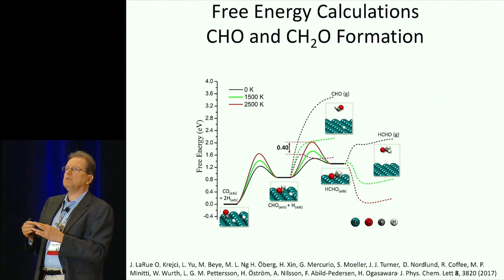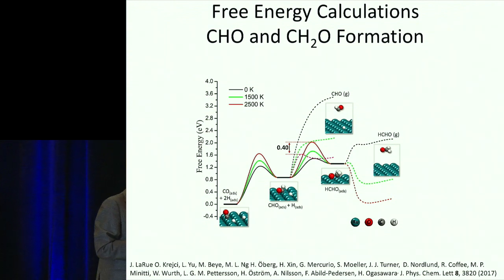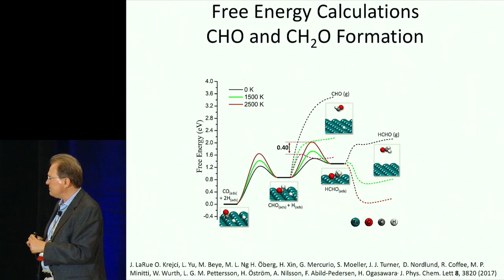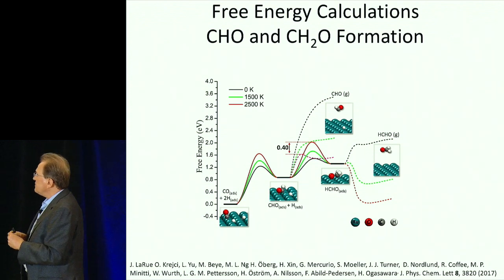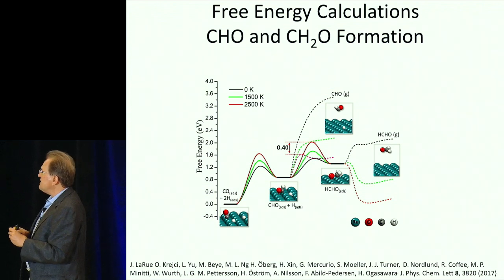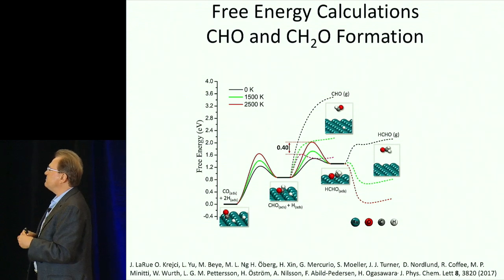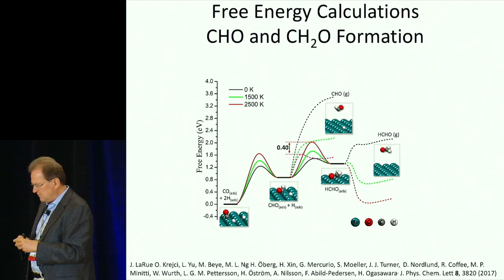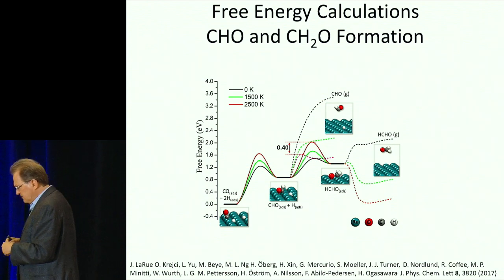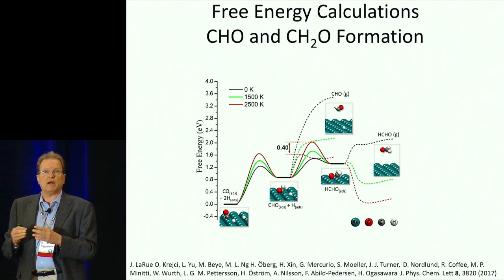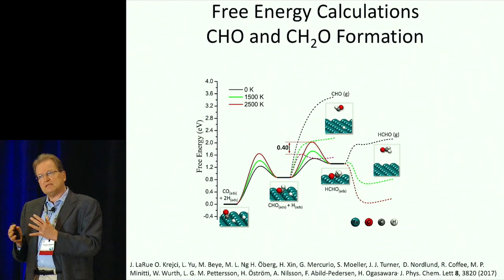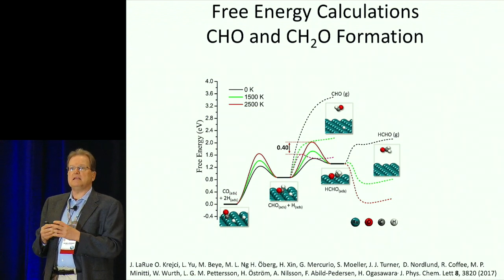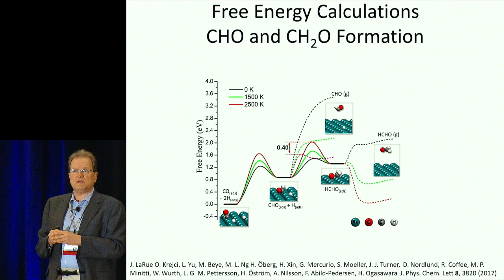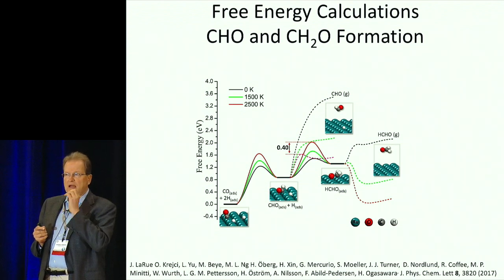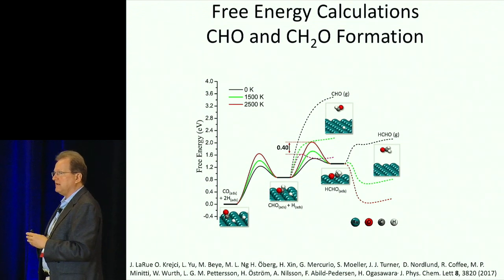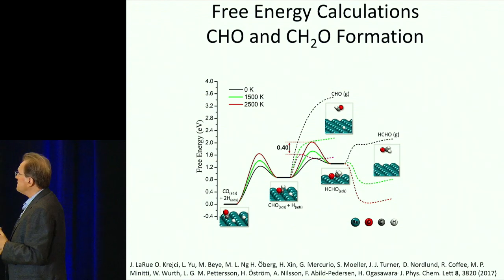If we add temperature, we get free energy, which of course corresponds to adding entropy into the system. And as you get it very hot, you can actually see that you can desorb these different species because the free energy of the gas phase, even though it's a radical state, becomes lower. That's why we could see it in the gas phase. So this demonstrates that indeed we can observe this CHO species. That is the first time this is seen in an experiment, and that it actually is indeed metastable.